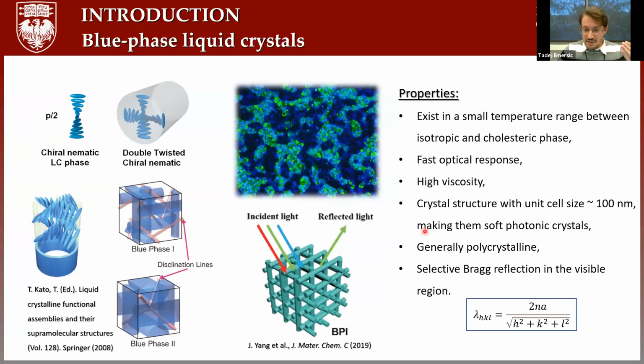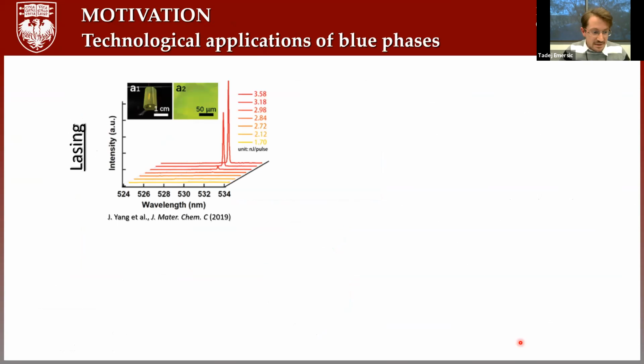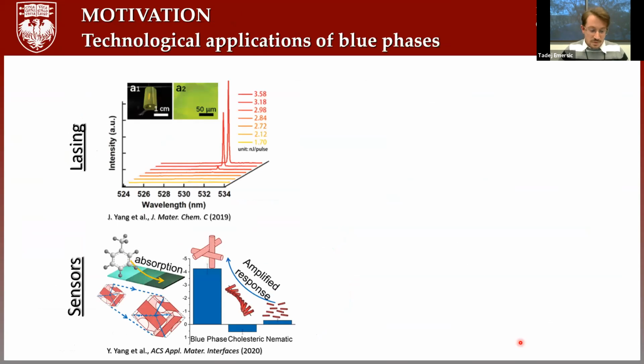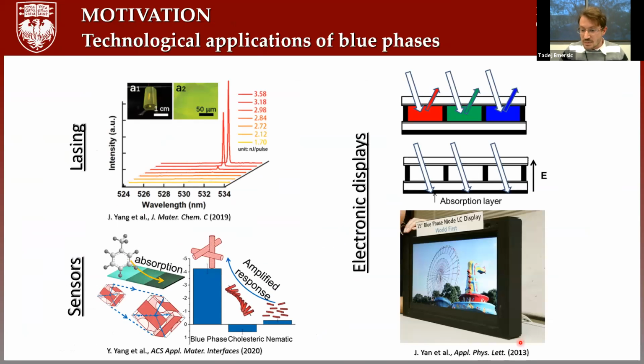They're generally polycrystalline, as we can see here, so that means they form many different domains of different colors. And we can see colors of blue phase because they have Bragg reflection in the visible region. We can get the peak of the reflected light according to Bragg's law if we know the unit cell size, the refractive index, and the Miller indices of the reflection plane. Because of all of these properties, blue phases are very promising candidates for different applications. For example, they can be useful in lasers and different kinds of sensors. And in 2008, Samsung already came out with a first blue phase prototype display.